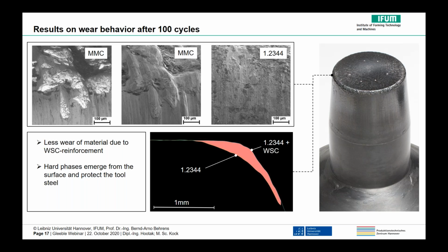The wear investigations show that the conventional tool steel is more affected by the process than the MMC materials. At the bottom of the slide, it can be clearly seen that the addition of the hard WSC phases prevents the material from being removed after 100 cycles in this experiment.